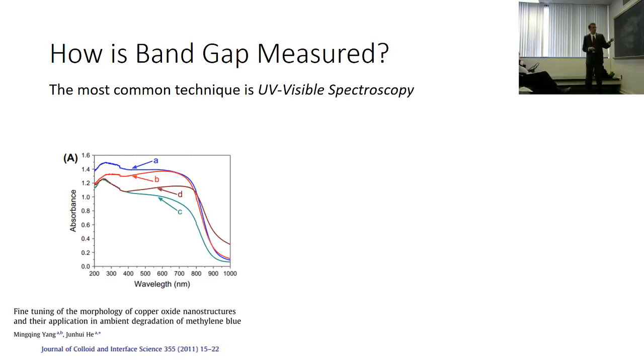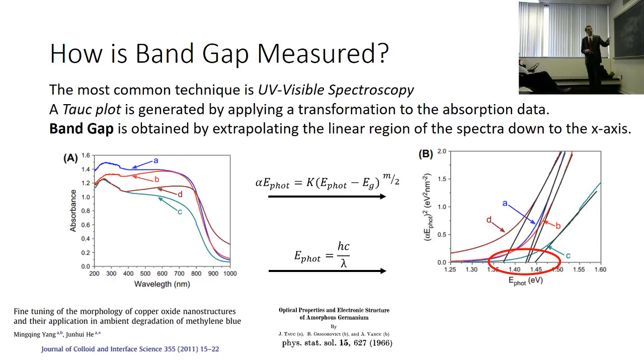So as a function of wavelength - this is from a different paper - you can get absorbance depending on wavelength. And what you do after that, to get the band gap from this, you have to do a conversion developed by the scientist Tauc in 1966. It actually makes it really convenient to find band gap. You extrapolate down the linear region of the plots to the x-axis, and where it intersects, that's your band gap.